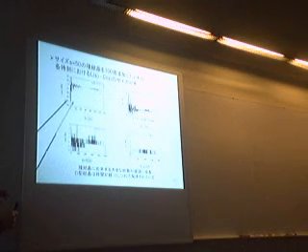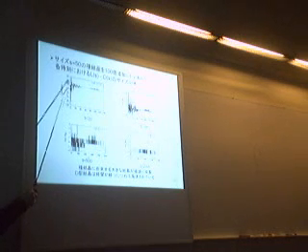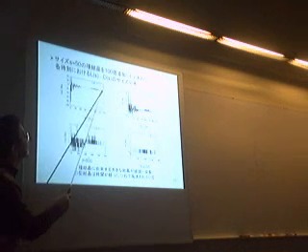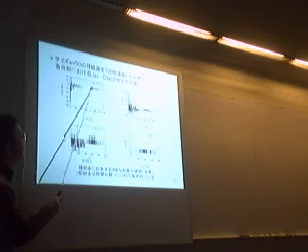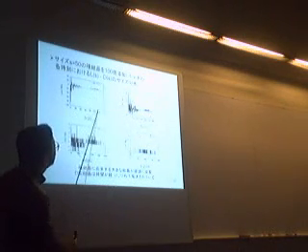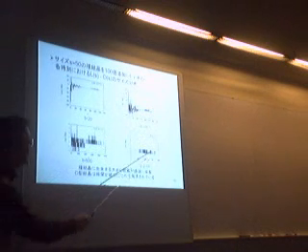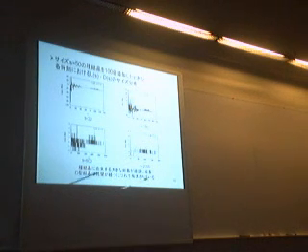This is the original added one, and this is the spontaneously growing crystal, small clusters, and they can be L or P. But the initially added clusters grow up to 100, 200, 600, and 1,000, and finally they soak up every small cluster because they are getting too large, and so Ostwald ripening takes place, and the larger cluster eats up the smaller ones.